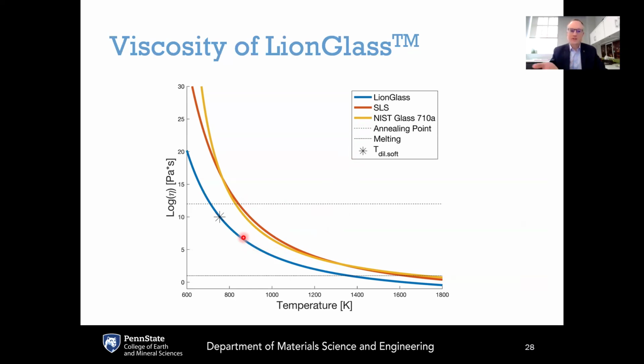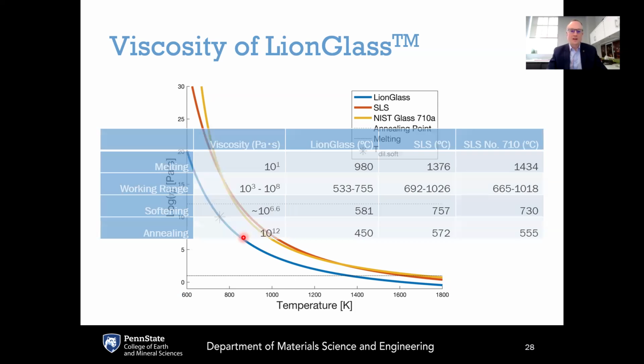So it's lowering the melting temperature, lowering the forming temperatures, but it's not giving a steeper viscosity curve, which is good because this means that we can control the forming behavior of the glass. One of the traditional issues with low melting temperature glasses is that the viscosity curves tend to be steeper, meaning a higher fragility, and that's not the case here for LionGlass.